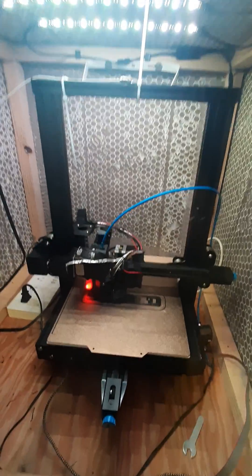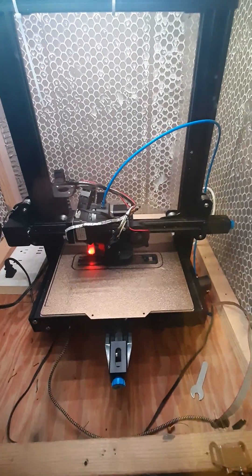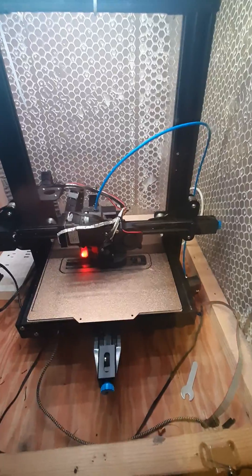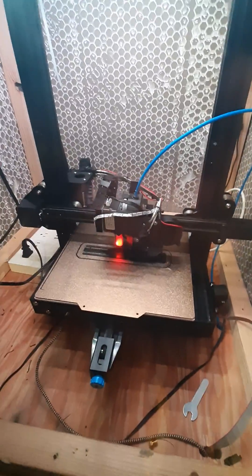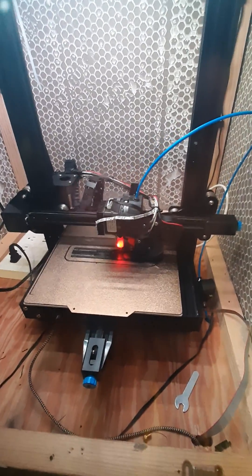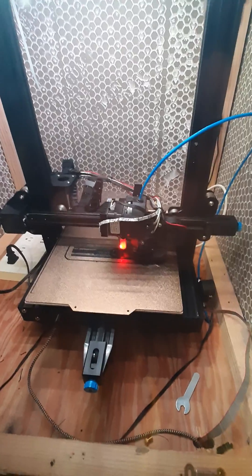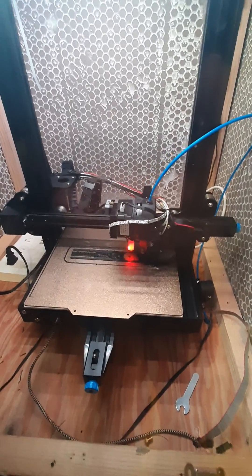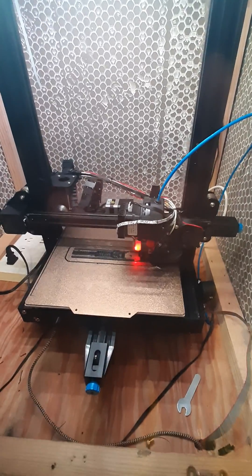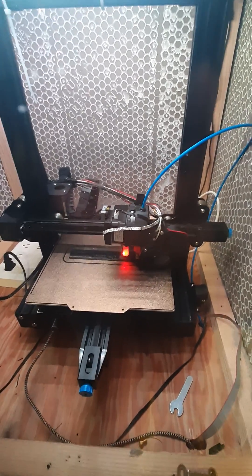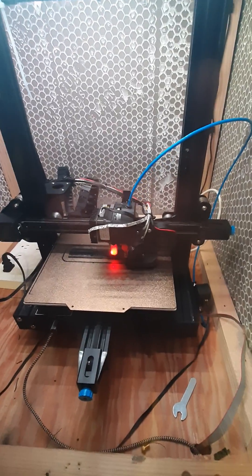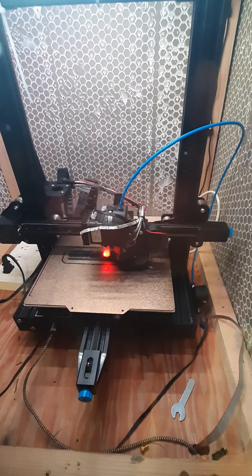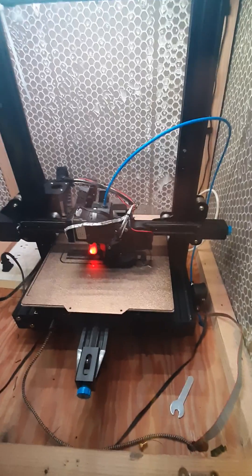Decided to keep my enclosure at about 130 degrees and this is Polymaker filament and they suggest about 260 degrees. But what I've found with that is it was still pretty brittle and I don't think it has a lot of carbon fiber, but it has enough to induce a little bit of brittleness.